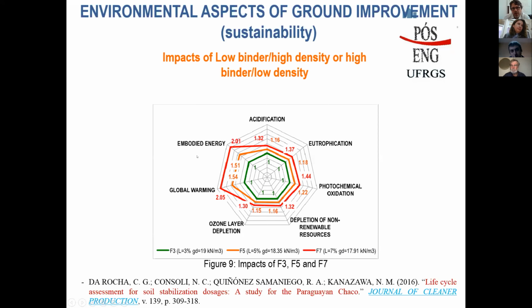Regarding embodied energy and global warming, we can show that if you use 3% of lime and higher compaction energy, versus something with smaller energy but a higher amount of lime, you get double the embodied energy and the global warming. It shows that it's better to compact more than to add more binder, for example, in order to get the same results.